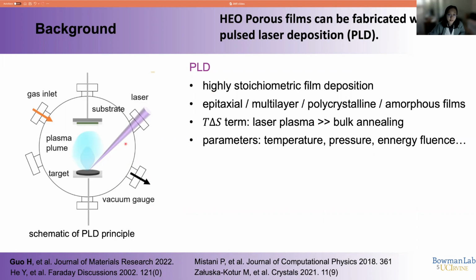First, the fabricated films have high stoichiometry with the target materials. Besides, they can achieve various kinds of film fabrication, like epitaxial films, multi-layer films, polycrystalline, or even amorphous films, by controlling parameters like the temperature, pressure, energy fluence, and so on.